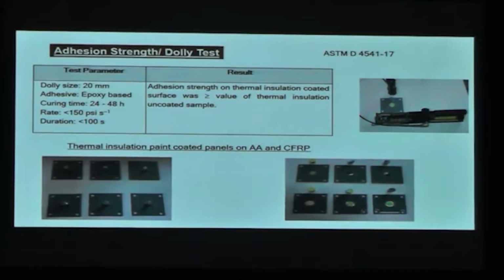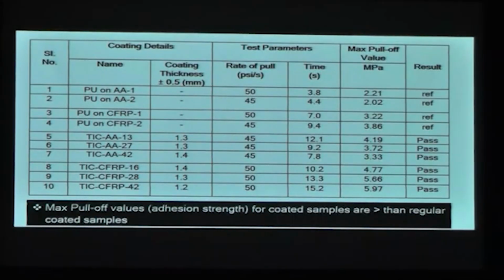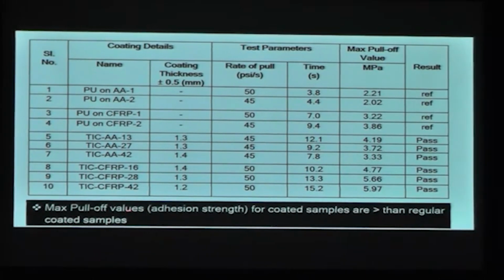So as said, adhesion was a very important factor to determine the service life of these aircraft coatings. The adhesion strength of these coatings was determined using the dolly test as per ASTM standard, using dollies of size 20 mm. Here the thermal insulation coated samples were tested against the conventional samples, that is the substrates with the normal, conventional aircraft grade BS2X34 polyurethane and yellow primer coatings. The tests were carried out as per the standard, and it was seen that the adhesion strength of the coated samples was much higher than the regularly seen values for the normal samples. So I can say that these coatings had very good pull-off strength compared to the regular coated samples.